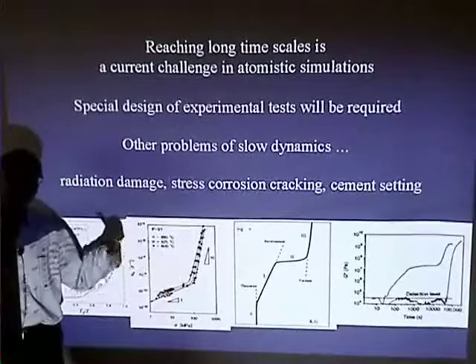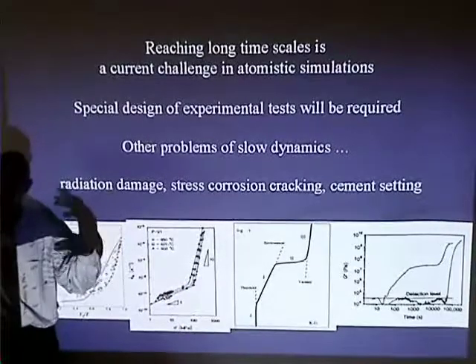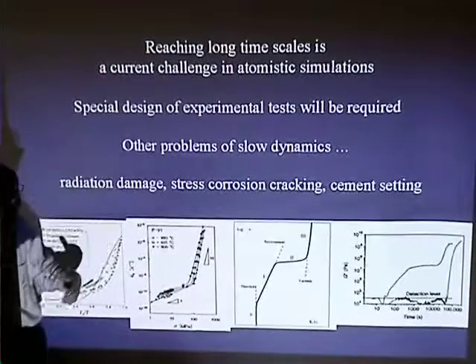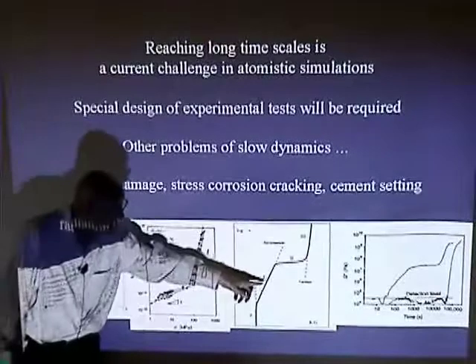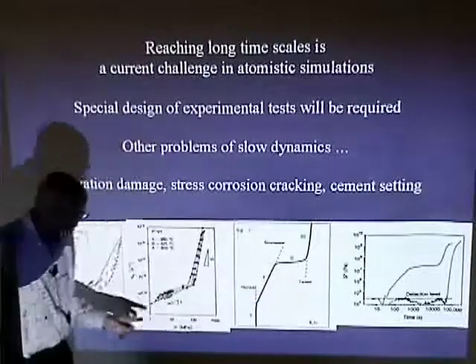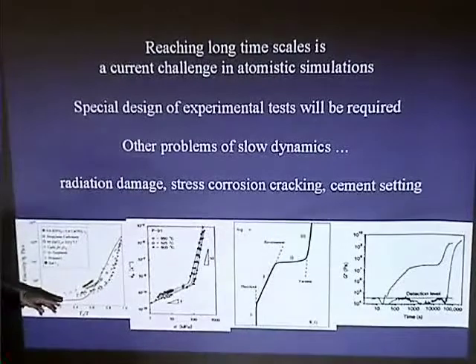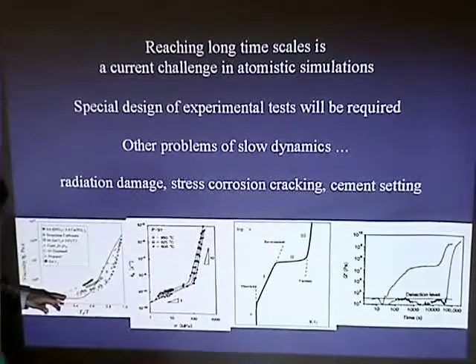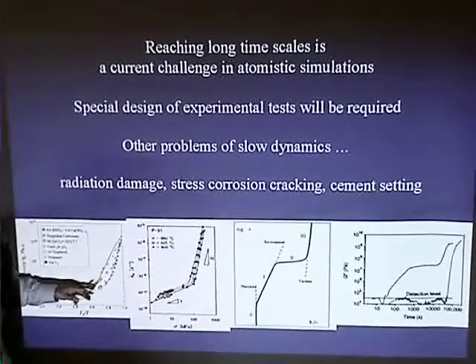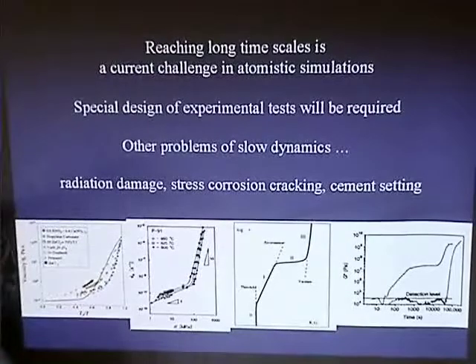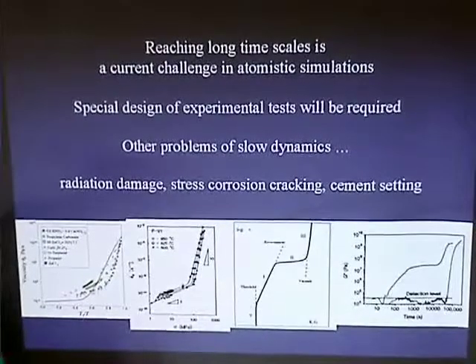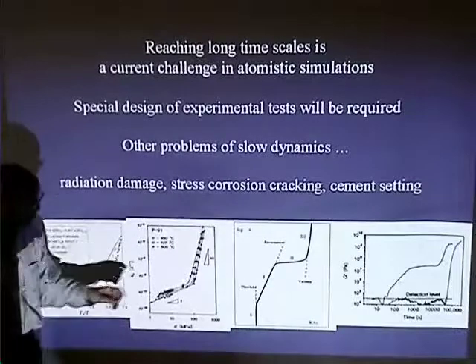We think it's the same sort of general underlying behavior: activation barriers and what have you. This would be a little different—these two are actually a little different. You can have a dynamical crossover from strong to fragile. But if this crossover becomes an extended crossover due to some additional degrees of freedom, like transport, then this crossover would give you a plateau.